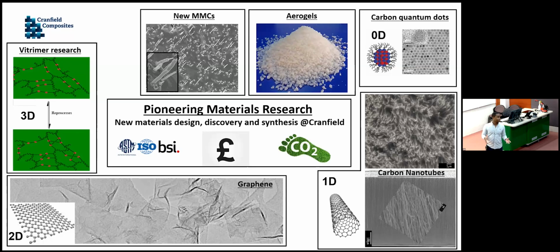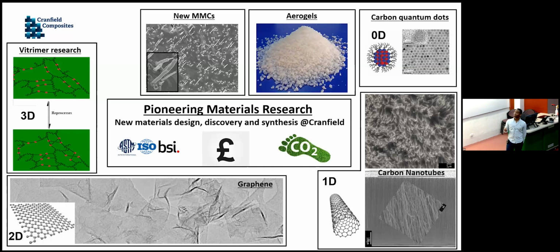from cracked methane. So you take methane, heat it up really, make it really hot, you make a plasma, and you crack the CH4 open, you get the carbon, and you get the hydrogen that you can use for energy. This process is already industrially available through a company that Christoph co-founded. It's called Levidian. I think I will mention them later. But they brand themselves as a nanosystems clean energy company, but essentially they sell these massive units where you can buy this thing. It comes in a shipping container. You plug it in, and you can get a machine that makes you graphene and green hydrogen, well, supposedly green hydrogen at the same time.